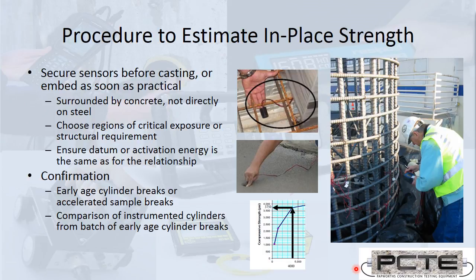Now, the final thing about maturity on site is we need to monitor what it's doing. It may be that conventional early age breaks are compared to results from on-site, or it may be that when the early age cylinders are cast and are being used as backup or as another QA tool, a maturity sensor is embedded into an additional cylinder which will travel with those site cylinders, and so when they're broken, there will then be a maturity check at that point. Because if materials shift or the mix shifts over the life of the project, you don't want your curve to be out of date. The curve may need to be reworked if the materials change on site.